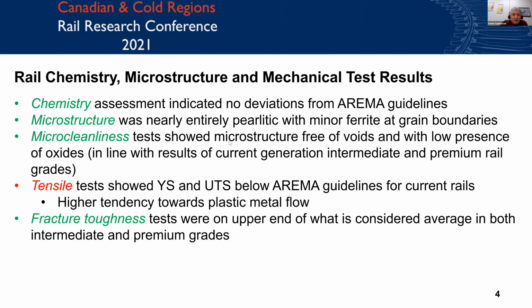We also did the fracture toughness testing on it, and that's supposed to tell you the resistance of this type of rail grade to winter conditions. And for this grade, the fracture toughness properties were fine. They were on average what you would see in today's intermediate rail grades and in premium rail grades. So the fracture toughness was not the issue here, but the tensile properties stood out.